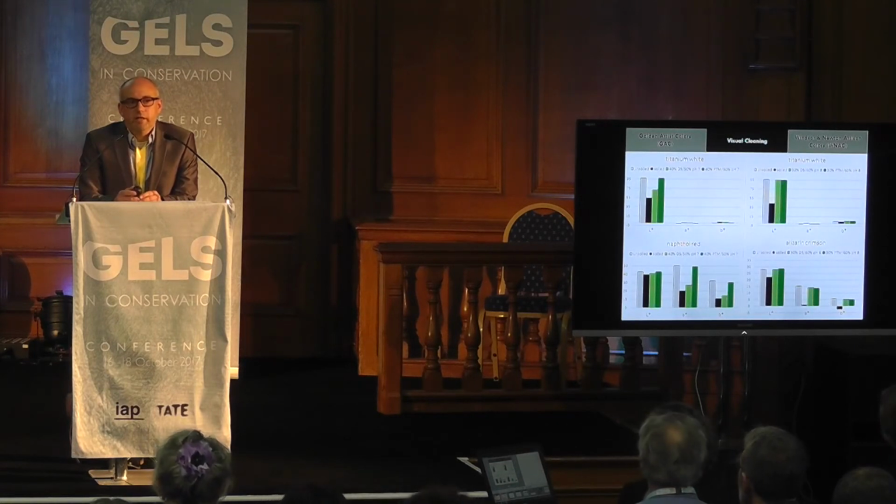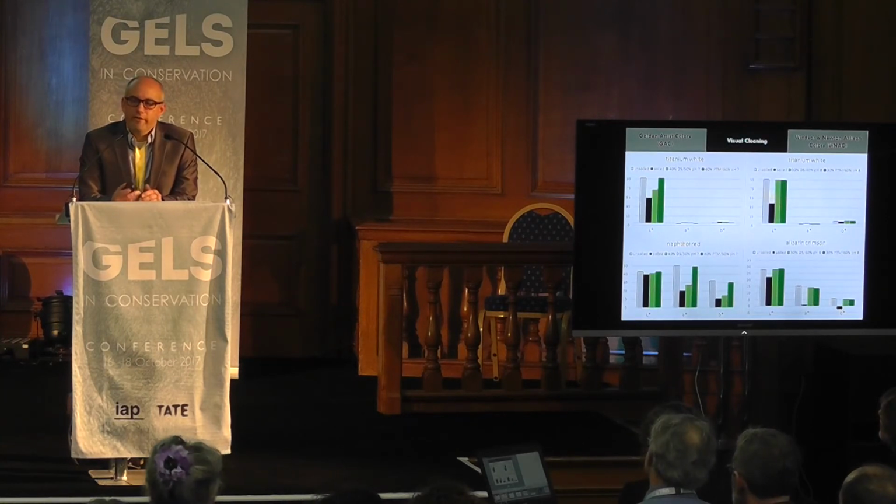What we see is that in these two paints considered here, the rest are considered in the publication, generally in the Golden Artist Colors, because of the presence of that alkyl phenyl ethoxylate, D5 cleaning systems are not going to restore the luminosity, are not going to restore the color. We have to work harder. We have to use that phenyl trimethicone-based solvent system in order to break up those associations. But if we do, we can restore the original color to those paint films.